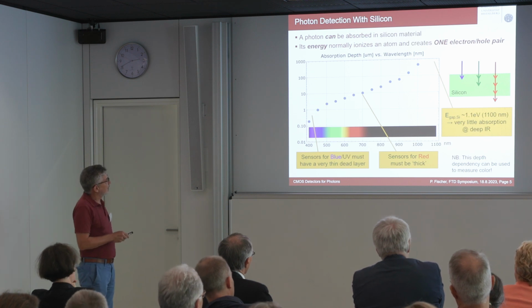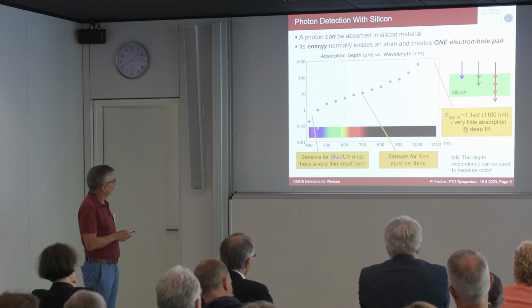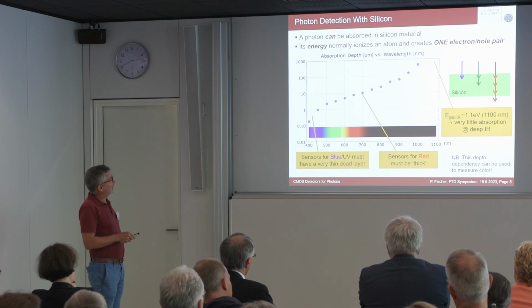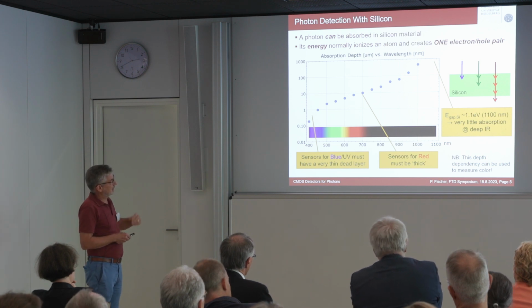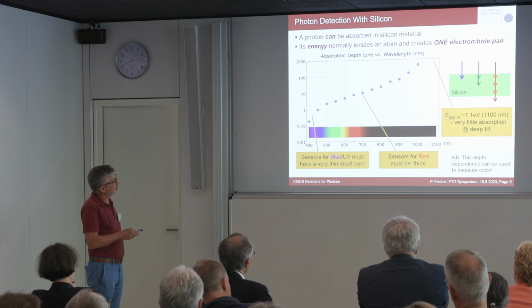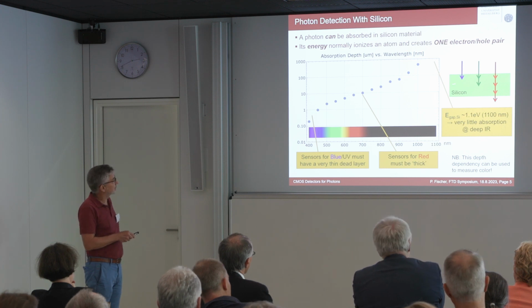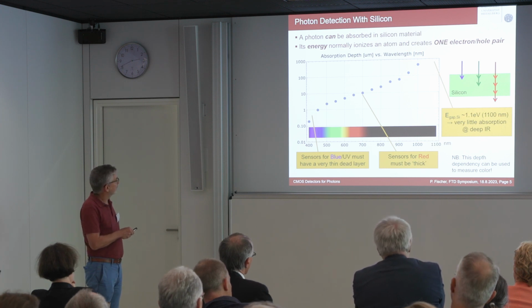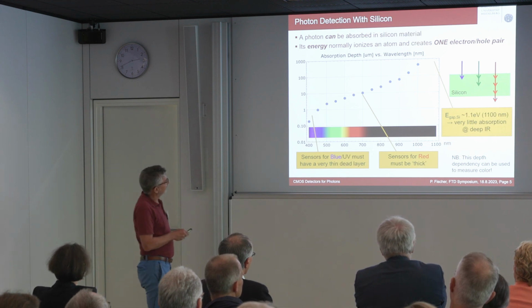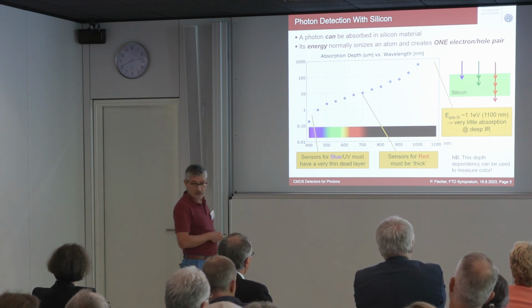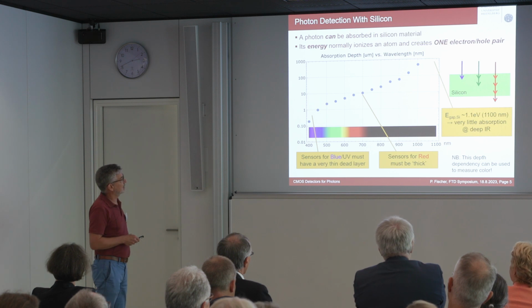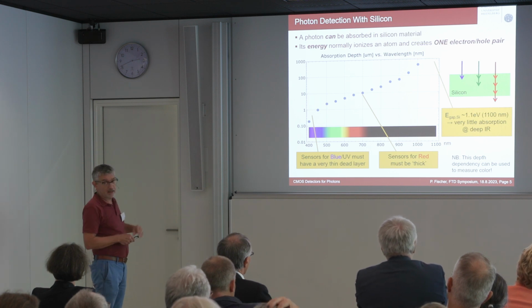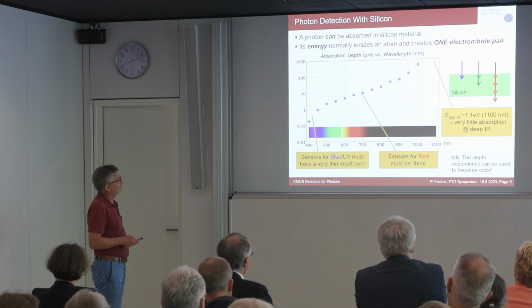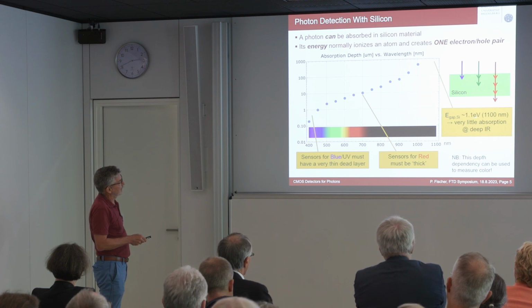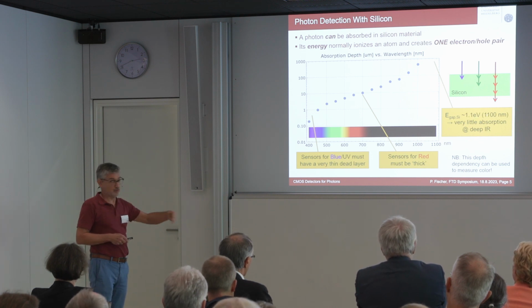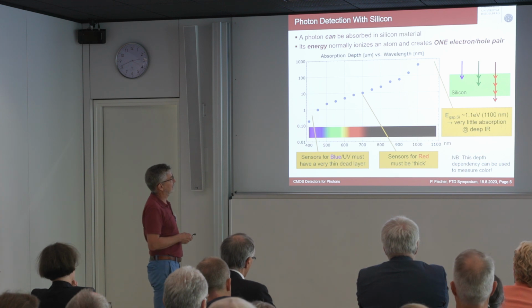If you have a blue photon, which has a short wavelength and a high energy, it can ionize atoms immediately. So this is why blue photons don't penetrate deep in the silicon. They are absorbed at the surface at roughly 1 micron. On the other hand, the red or even infrared photons have very low energy, and they have a hard time to ionize the atoms, and eventually, if they are too infrared, they will go through the silicon. Silicon becomes transparent for infrared light.